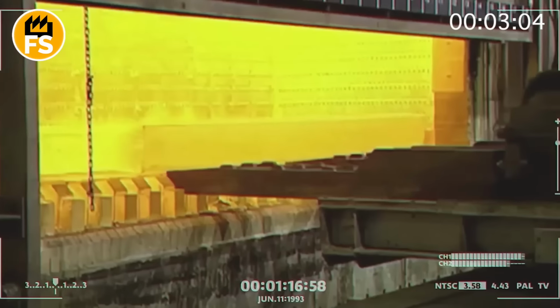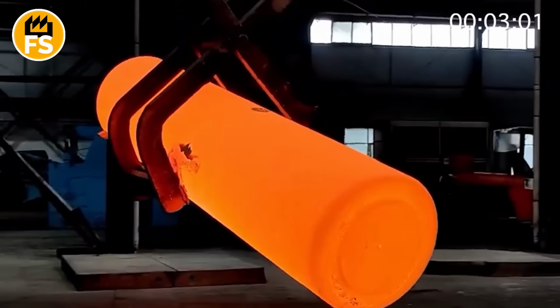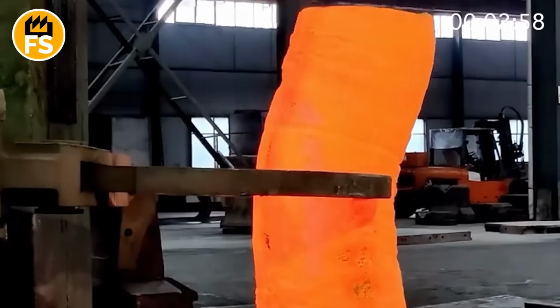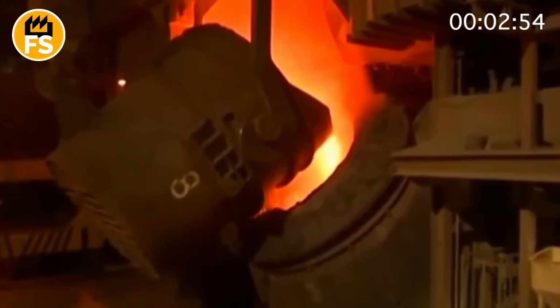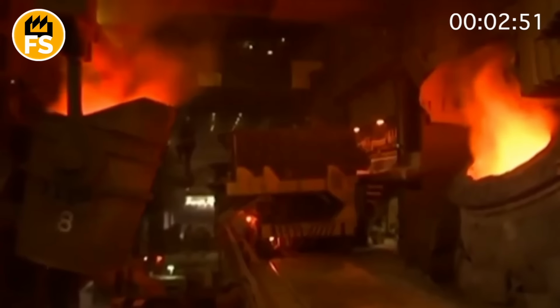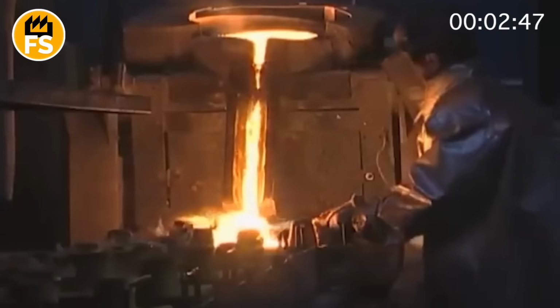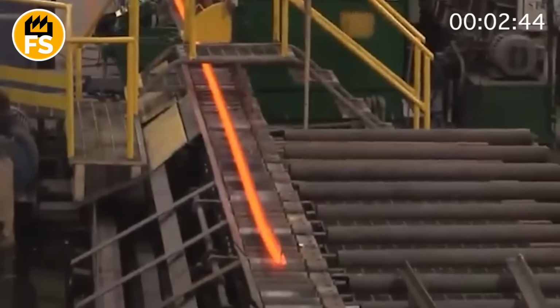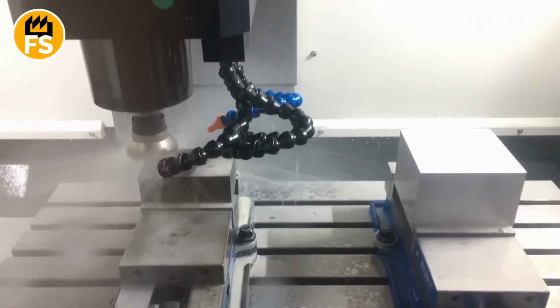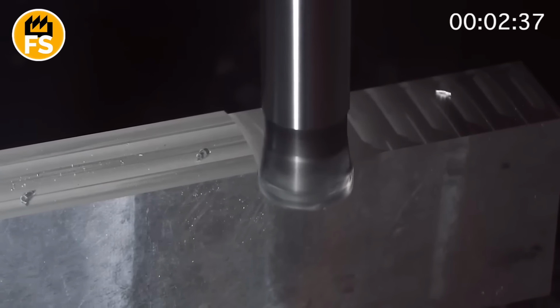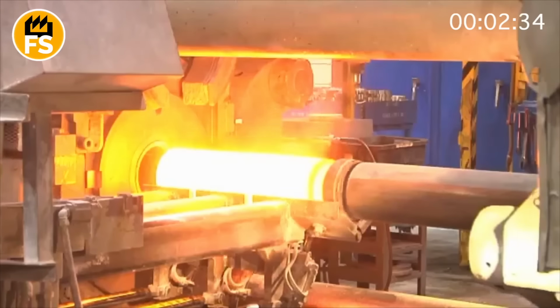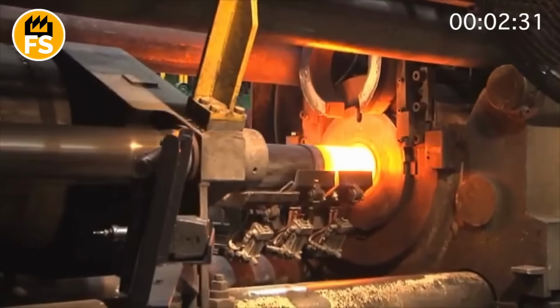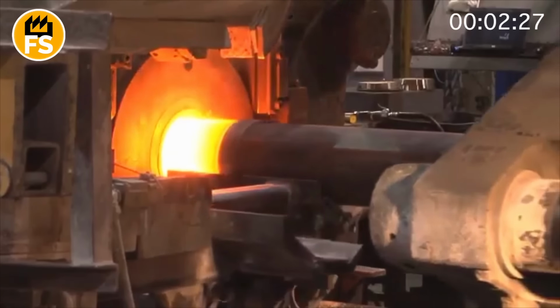First of all, titanium ingots can be used to create titanium alloys, mixtures of titanium with other metals that improve its properties. To obtain an alloy, alloying elements are added to molten titanium, most often aluminum, vanadium, molybdenum, iron, or niobium. These impurities change the metal's structure, increase its strength, heat resistance, corrosion resistance, and improve its processability. The production of alloys usually takes place in vacuum arc furnaces, where the metal is melted at high temperatures in a protective atmosphere to avoid oxidation. To achieve a homogeneous composition, the alloy is remelted several times, and after that, it is cooled and prepared for further processing.